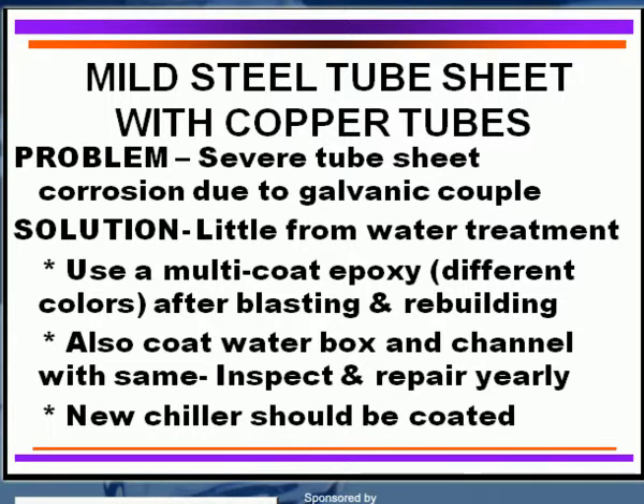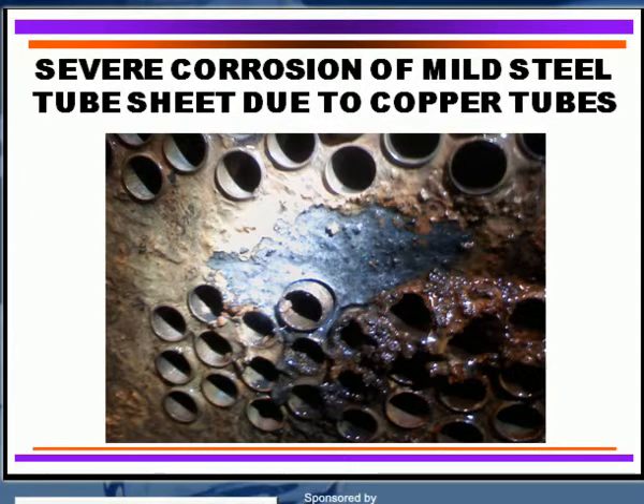because this is contributing, of course, mild steel, iron oxide if it's corroding. And if you have a brand new chiller, the ideal thing is to get the tube sheet coated with epoxy prior to actually putting it in service. A number of manufacturers can do that for you before they deliver the chiller, or you can do it directly once you install it, by taking it offline and putting the epoxy coating on it.